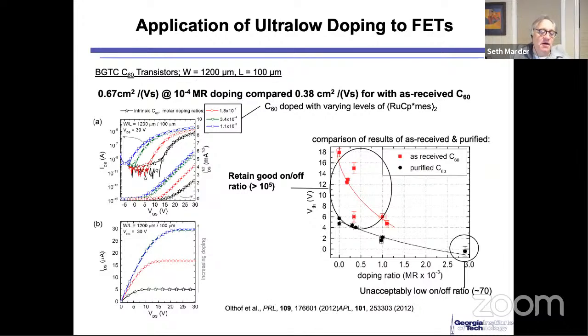And colleagues like Bernard Kippelen think it's absolutely critical for people to see that you have very good data. And there's good data. Let's focus on the right side of the slide. So what we did in this experiment is we took as received pure C60. This is a high quality C60 that we got from Aldrich. Then we took that material and we sublimed it, I think, 3 or 4 times. And then it was very, very pure.